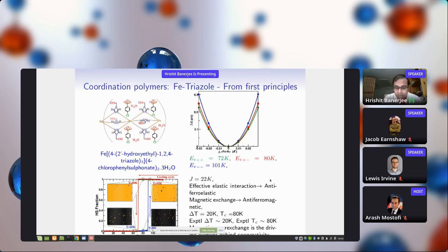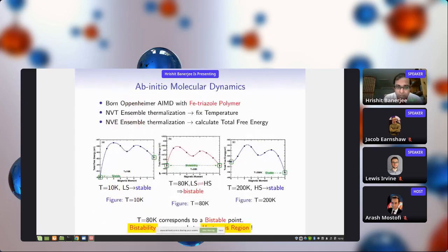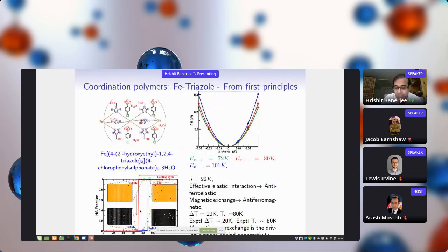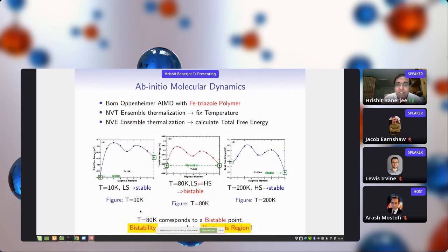To further confirm without any modeling, we do ab initio molecular dynamics. These are mostly Born-Oppenheimer AIMD, and this is a combination of NVT and NVE. And we find that at 10 Kelvin, our low spin state is stable. At 80 Kelvin, we have a bistability, which is the center of this hysteresis region. And as shown experimentally in the very beginning, there is a bistability which confirms the hysteresis region.